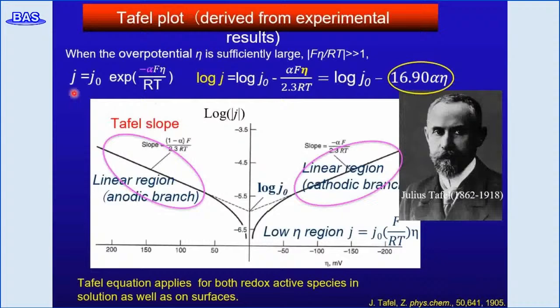Taking logarithm on both sides of these equations leads to equation 1, which is known as the Tafel plot. A plot of log current density versus overpotential provides useful information about the exchange current density and transfer coefficient from the linear region, called Tafel slopes. Tafel found this equation from experimental result in 1905, which was rationalized later by Butler-Volmer equations using transition state theory.